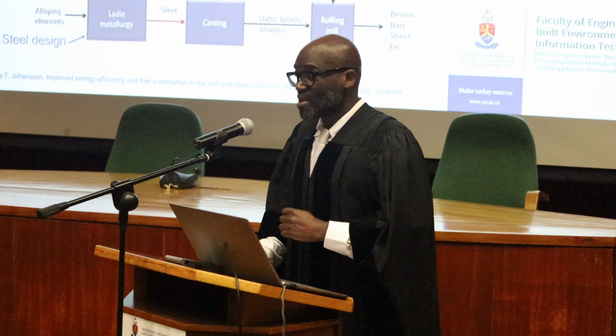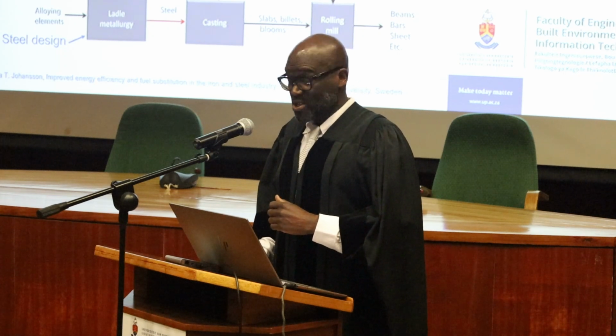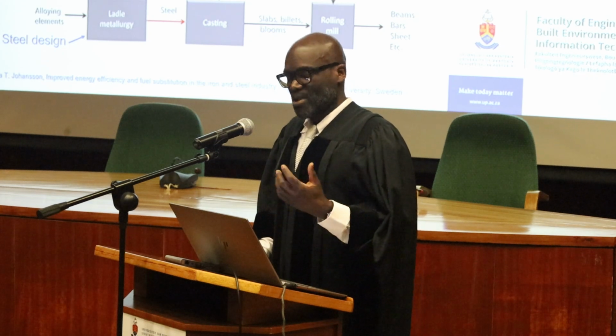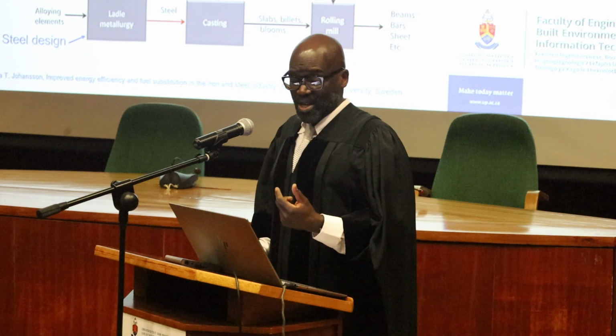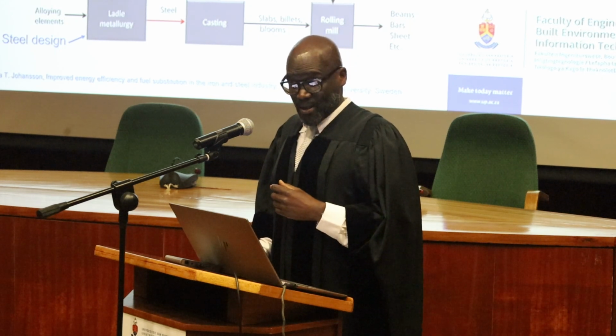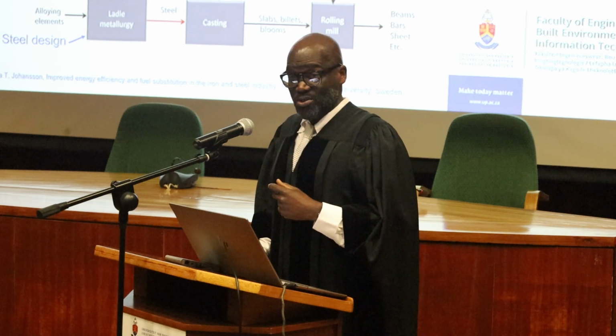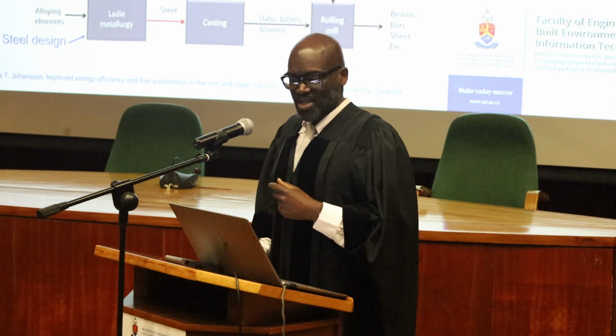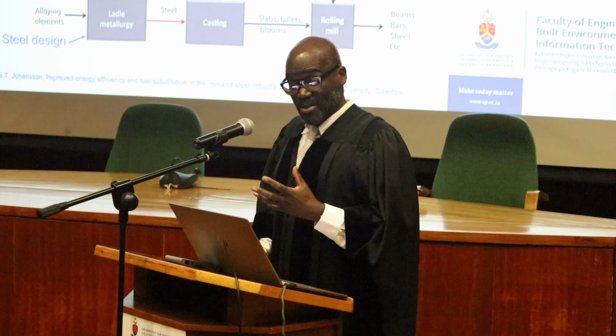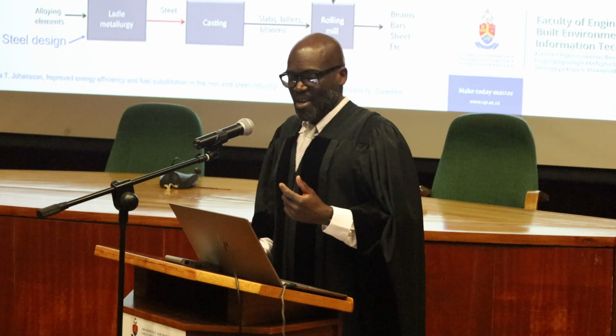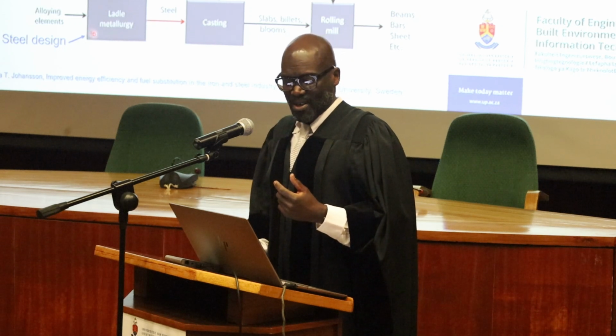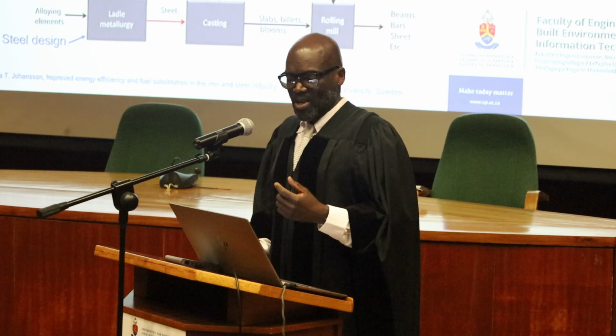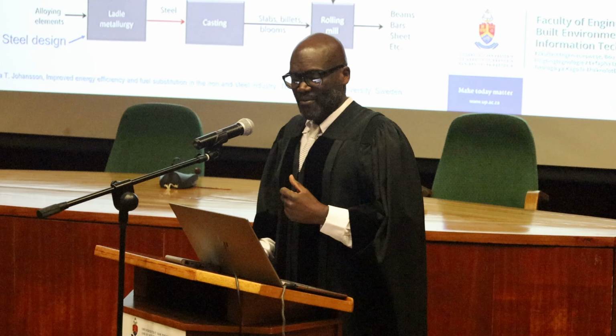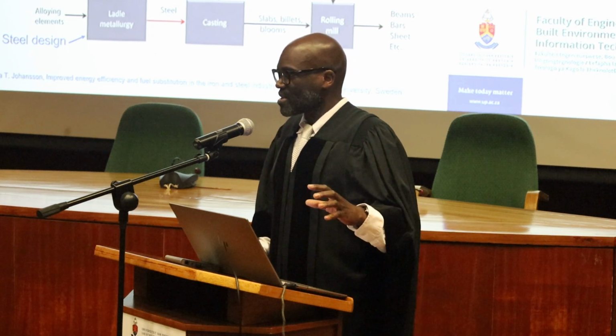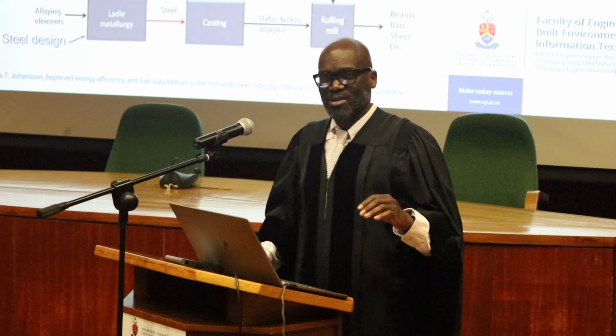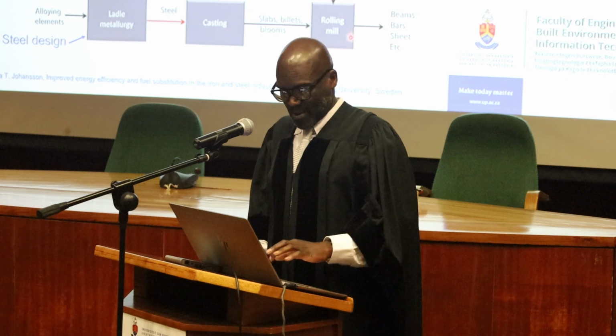So as things stand now, this is what we have today. We have the traditional coal route and the hydrogen, but mostly also the natural gas, which are hydrocarbons. And if hydrogen is going to be used as a reducing agent, this will be the process route. So it will be direct reduction iron, which is DRI, then electric arc furnace, and you end up with crude steel, which is processed further. And the steel design starts here, where now the steel is tweaked to fit purpose. Then after that, it is cast, then rolled into long products, the products that we see, flat sheets for iron sheets, pots and pans. That is done here now.